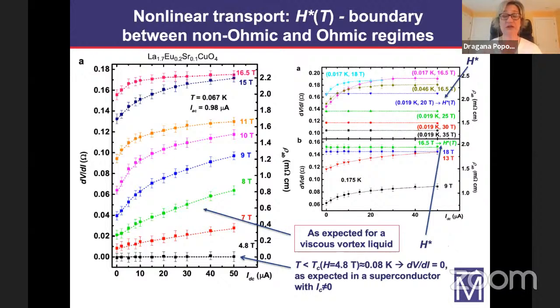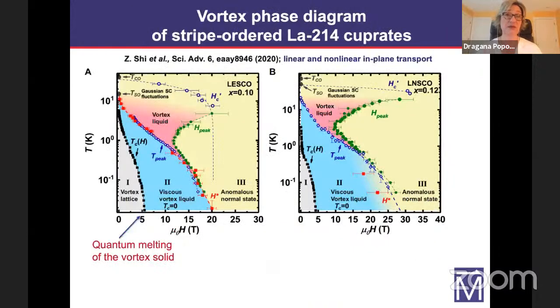So based on what I already described, you can construct the vortex phase diagrams for these materials, and this is shown on this slide. So here TCs are shown with these black symbols. You can see in both materials, TC is suppressed to zero at a relatively low field of only about 5 Tesla. So this is the quantum melting field of the vortex solid.